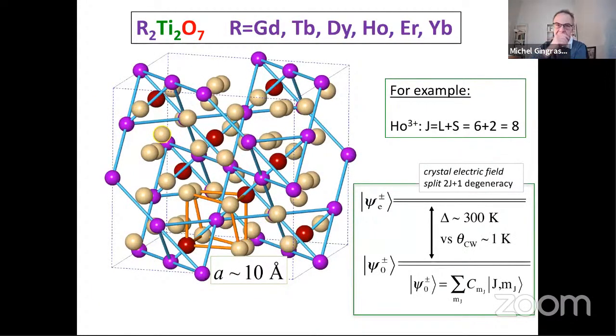People then started investigating these materials very extensively, and this is where the discovery of spin ices came about. So, focusing on the titanates, because these have been the most studied, because they can be grown as very large single crystals using an image furnace.